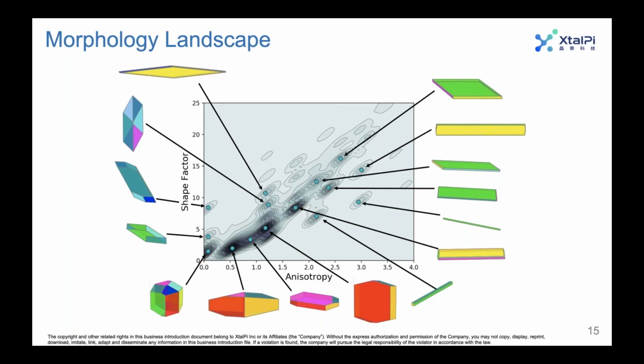For each morphology, we can calculate those descriptors, plot it, and then we can calculate the kernel density estimator based on the types of morphologies for that system. So a denser area of this plot means that there are more morphologies that are potentially available within that region. So in this case, we see that there is the potential for lots of prisms or plate-like structures suggested by this morphology landscape.